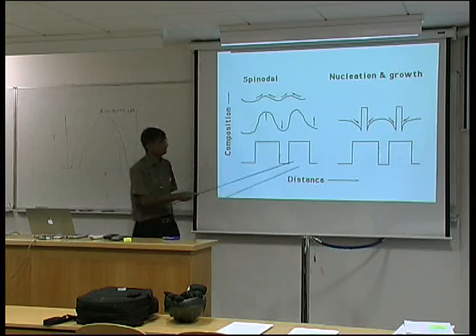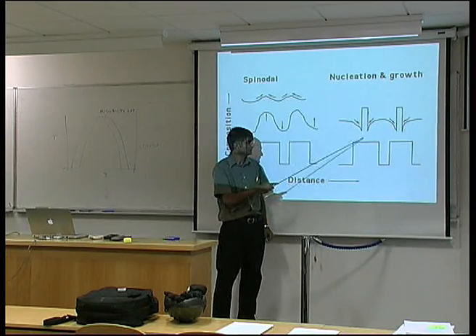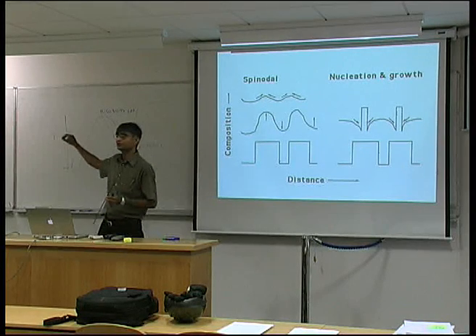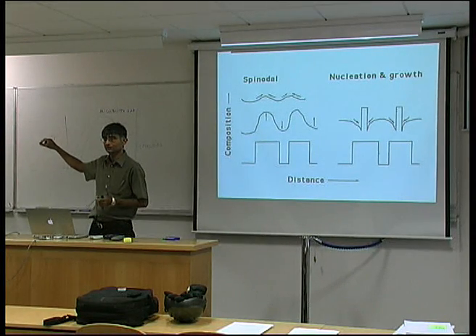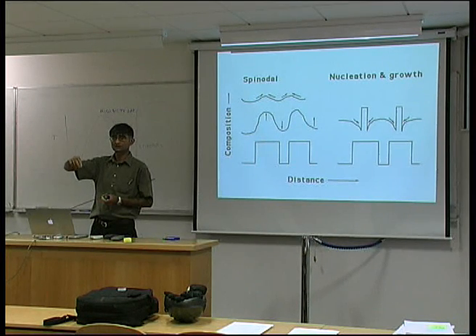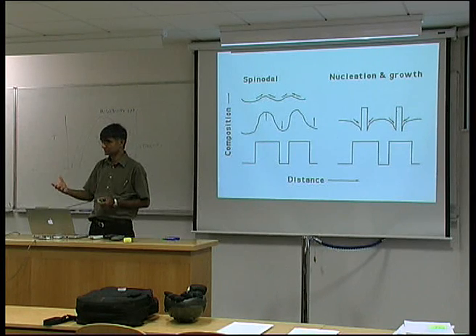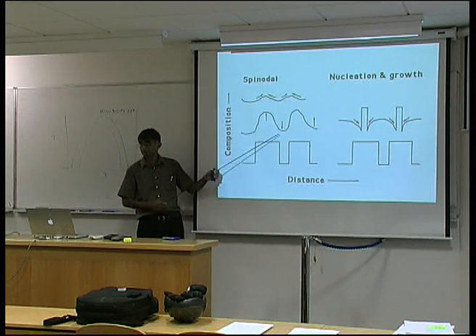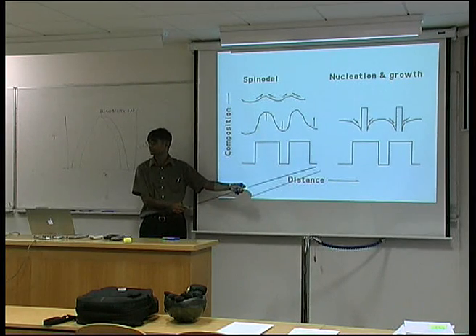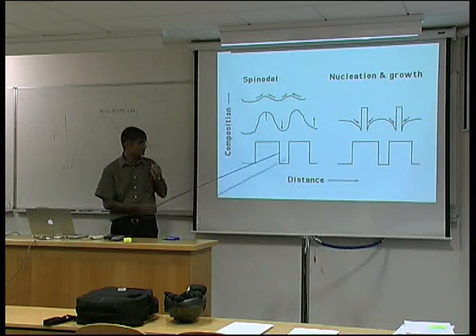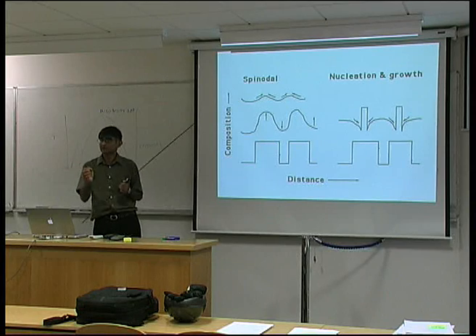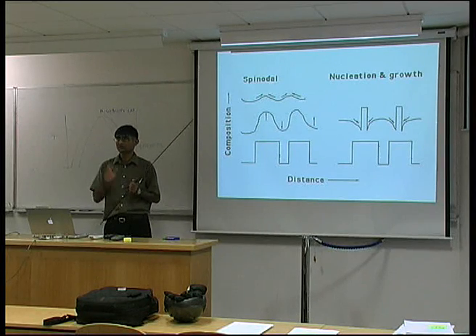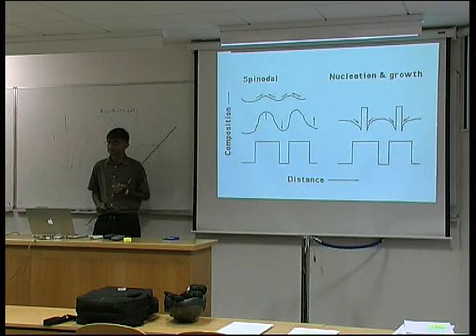In the nucleation regime, you need to nucleate a phase - a particle - which then grows with a constant composition. When it nucleates, it already has the equilibrium composition given by the common tangent. If in an experiment you find that the very smallest particle already has the right composition, it cannot be spinodal decomposition. In spinodal, even the tiniest perturbation will grow by uphill diffusion until you finally reach the equilibrium composition. It's straightforward to distinguish experimentally by doing chemical experiments on a very fine scale.